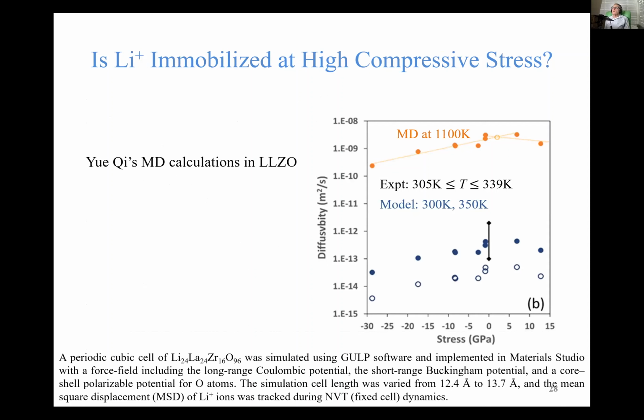So you might ask, well, if the compressive stress is so high, then how is lithium going to move around? The atoms are crowded, we just said. And so that's a fair question. So my colleague Yue Qi did some molecular dynamics calculations in LLZO and just said, well, what happens to the diffusivity of lithium if you introduce overcrowding or undercrowding in this lattice? And so she took the stress level from 30 gigapascal compressive to 15 tensile. These are ridiculous levels, but in a computer, you can do anything. And so she did the calculation at 1100 Kelvin because that speeds up the process, and then extrapolated it down to either 300 Kelvin, shown as open circles, or 350 Kelvin, shown as these dots.